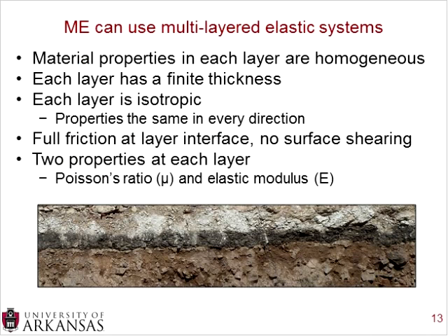So you can see in the picture on the bottom here, this is a cross-section of a pavement. It's actually a pavement down in Little Rock, Arkansas on I-630. At the bottom of this pavement structure is the subbase. That's the brown dirt. And then there's a thin layer, about 6 inches, of asphalt stabilized base. And then there was approximately 15 inches of Portland cement concrete on top of that. So when you're thinking about trying to define the pavement structure in these layers, you can really see that nicely in the cross-section of this pavement structure down in Arkansas.